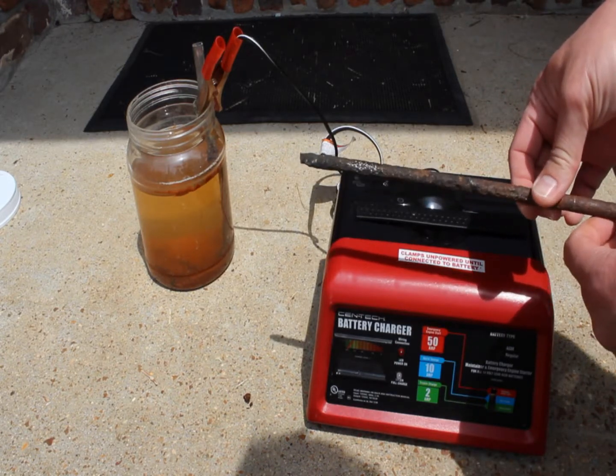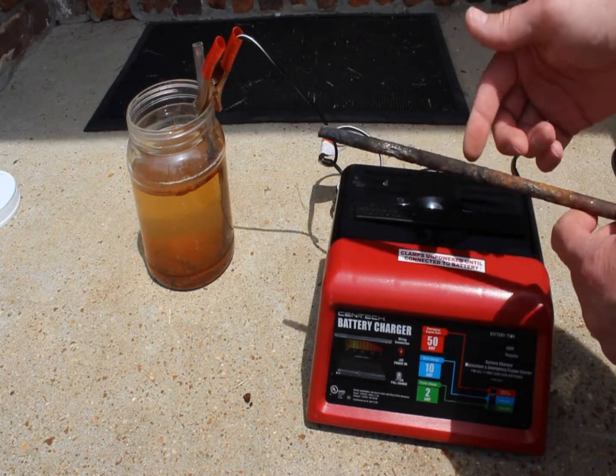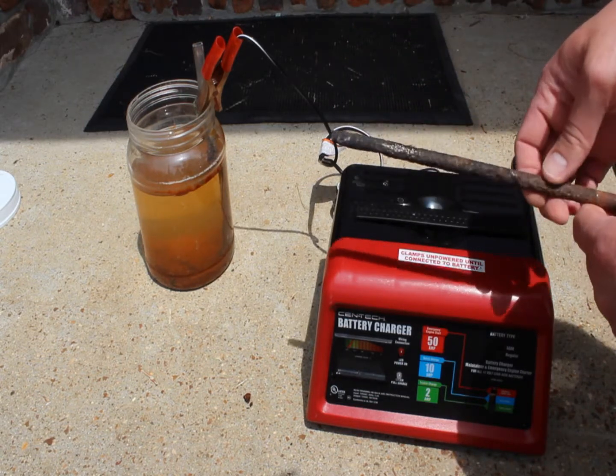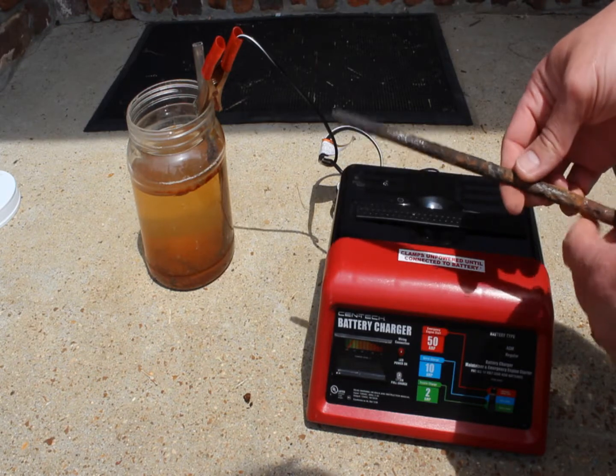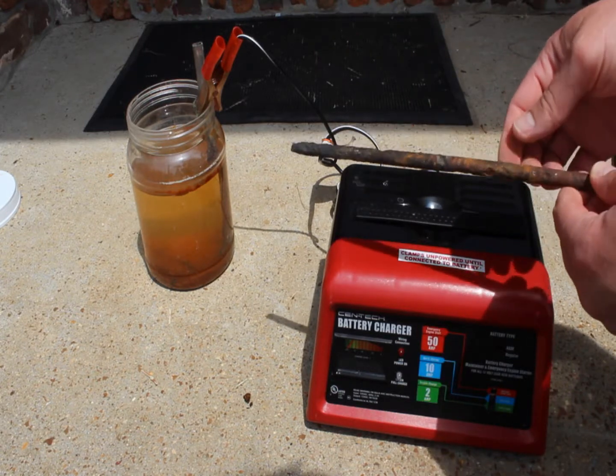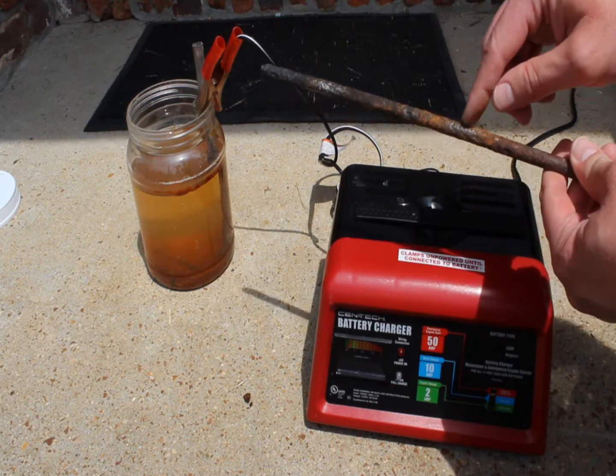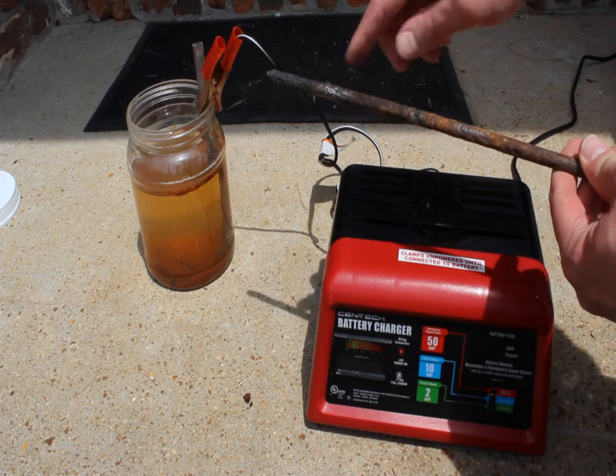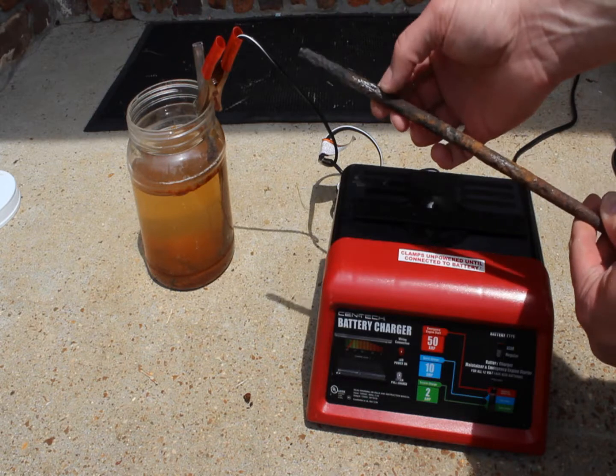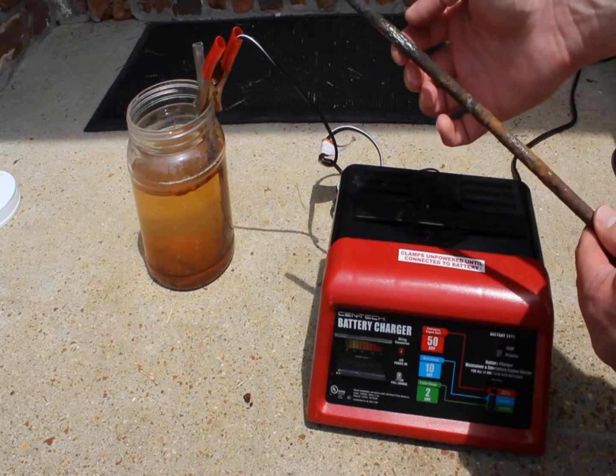You can tell just how badly pitted this is. When I pulled it out there was no rust at all from this line down. You can see how quickly it's already rusted back — just a matter of minutes. I hit it with the wire brush here twice as long as I did down here and you still can't see the bare metal — there's still a layer of rust on this part. But you can clearly see the bare metal here where the pitting isn't.